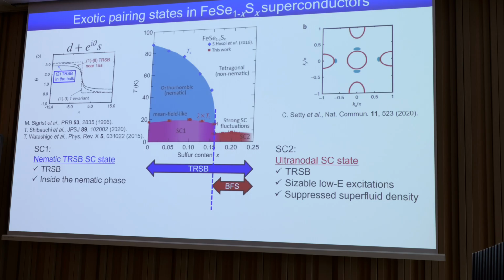If you consider the nematic domain boundary, let's say here, you should have a D plus S state on the left-hand side, but a D minus S state because of a different geometry of the system. This problem was already discussed long ago for orthorhombic YBCO by Manfred. I talked to him, and he immediately had the idea that you could have a sign changing order parameter with this e to the i-theta prefactor near the domain boundary, which can induce the time reversal symmetry breaking state inside the nematic phase.